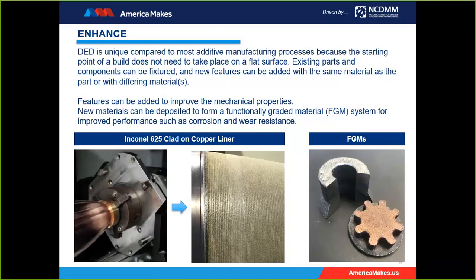One of the unique abilities of DED is its ability to enhance existing parts. It is unique in the fact that it doesn't require a flat surface to be the starting point. Existing parts can be brought into the system and have materials added to it by the DED process. Geometric features such as ribs and collars can improve mechanical properties. And new materials can be added to create functionally graded material, or FGM, systems, to improve the properties compared to the base material. On-the-fly powder blending or unique powder feeding systems can create gradient transitions to reduce residual stresses between layers of differing materials during the process.